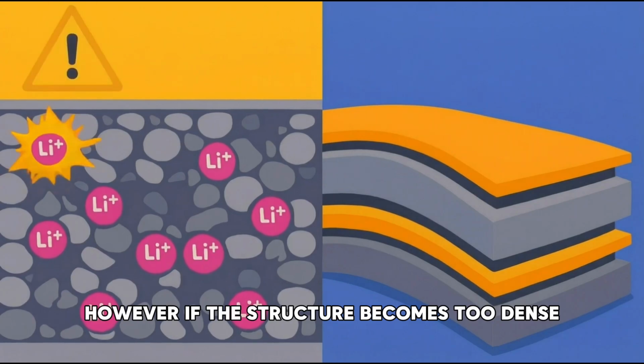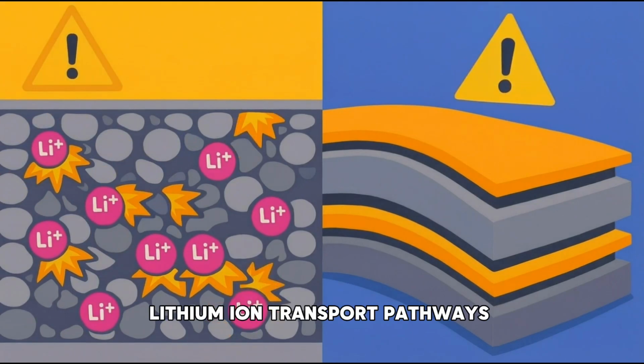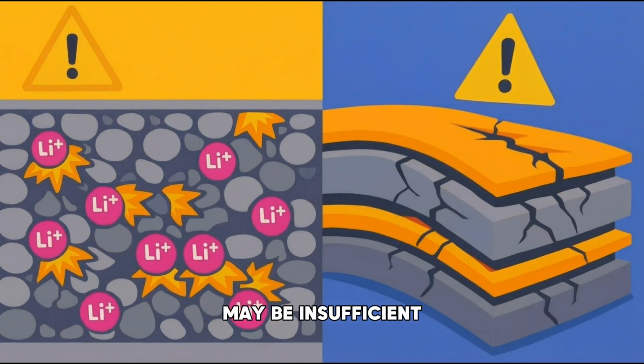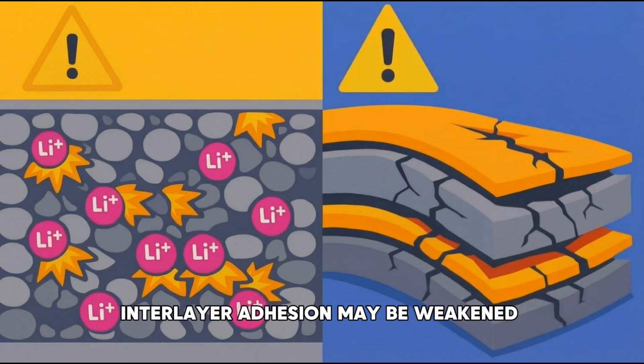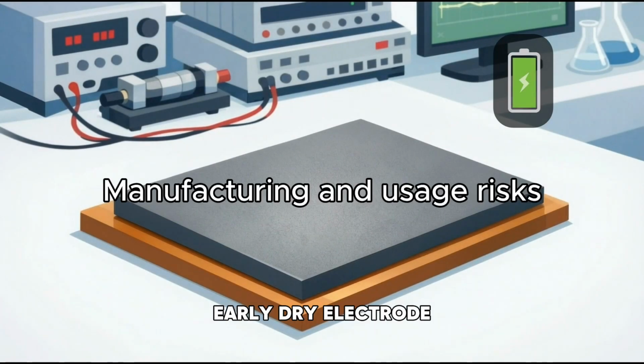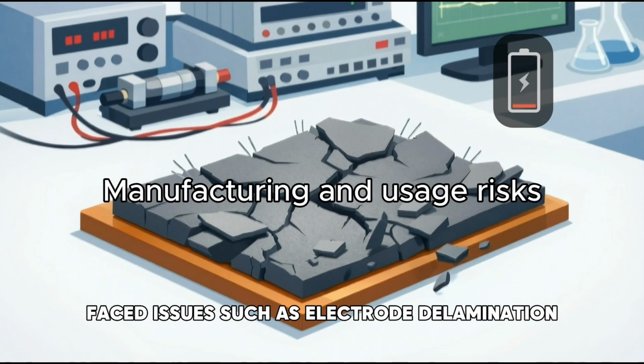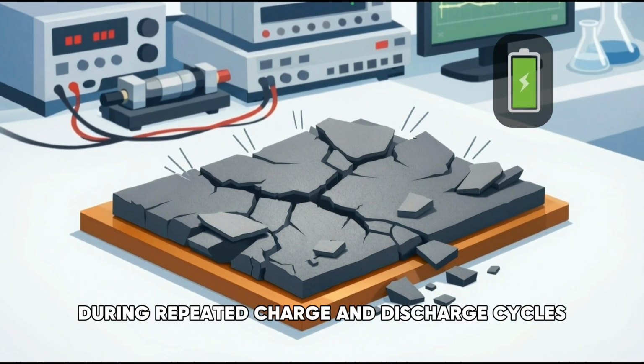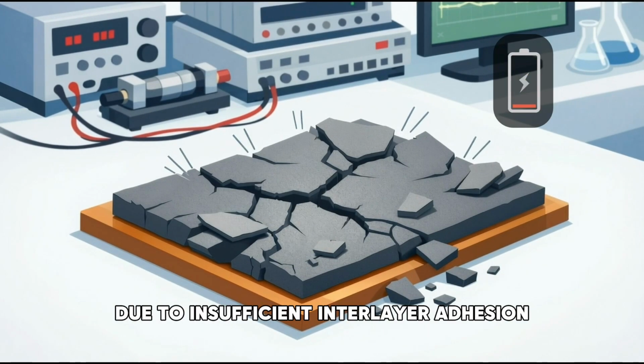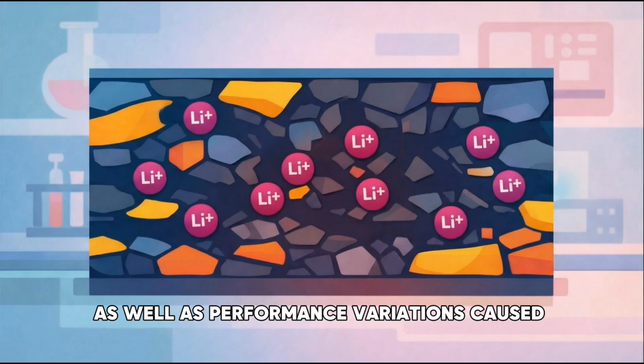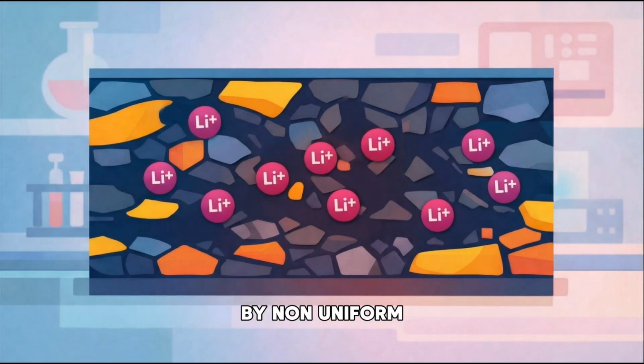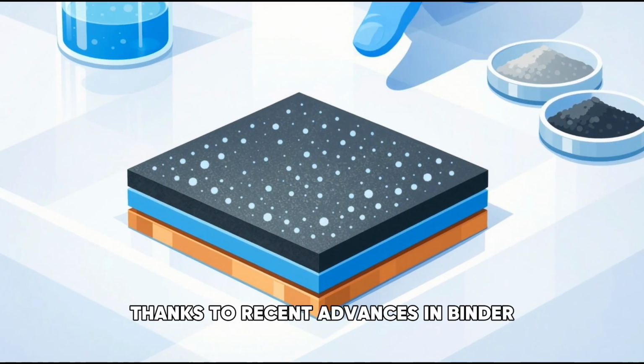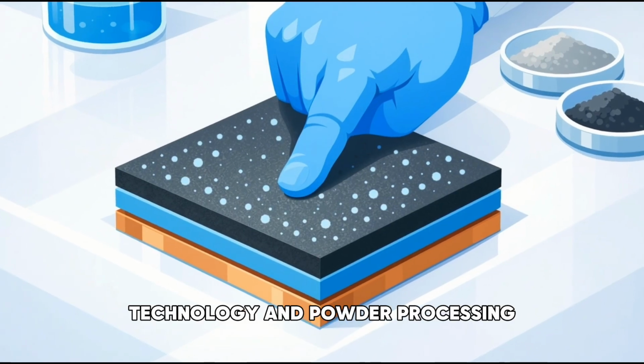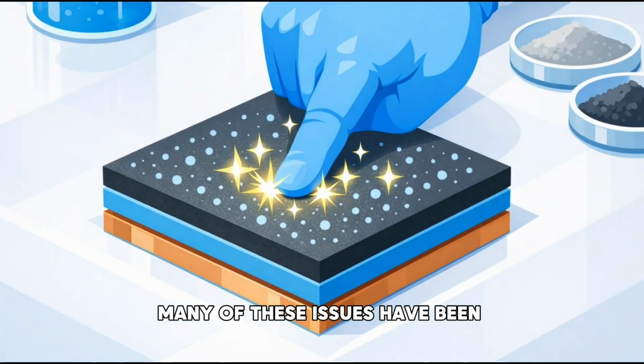However, if the structure becomes too dense, lithium-ion transport pathways may be insufficient, and if compression is uneven, interlayer adhesion may be weakened. Early dry electrode coating technologies faced issues such as electrode delamination during repeated charge and discharge cycles due to insufficient interlayer adhesion, as well as performance variations caused by non-uniform ion diffusion paths. Thanks to recent advances in binder technology and powder processing, many of these issues have been significantly mitigated.